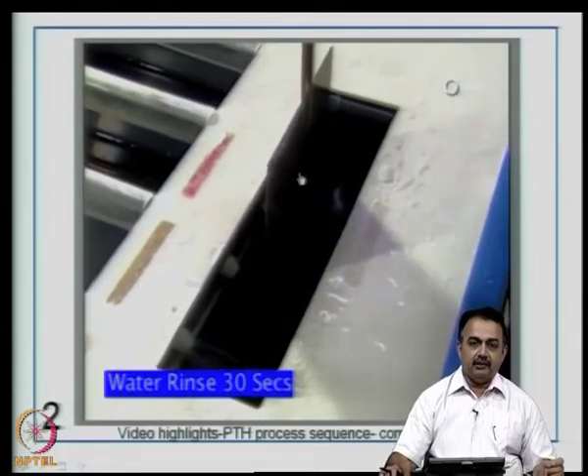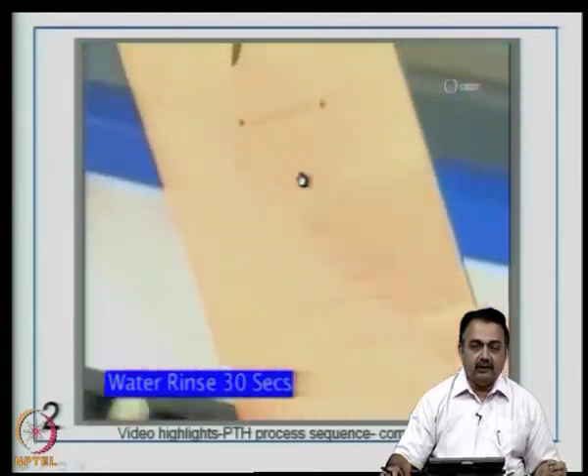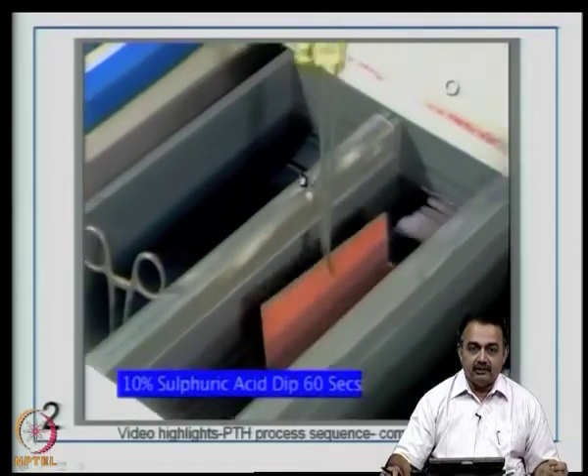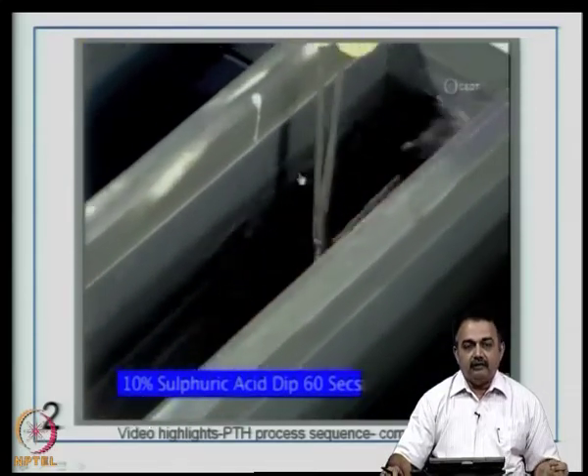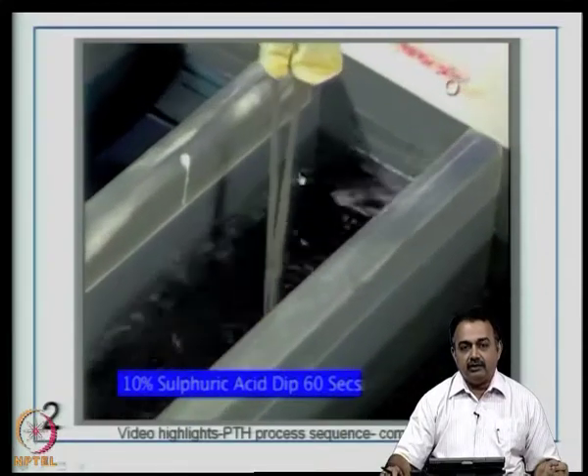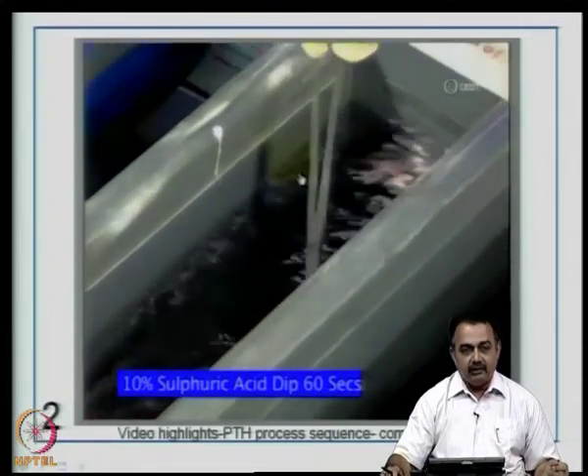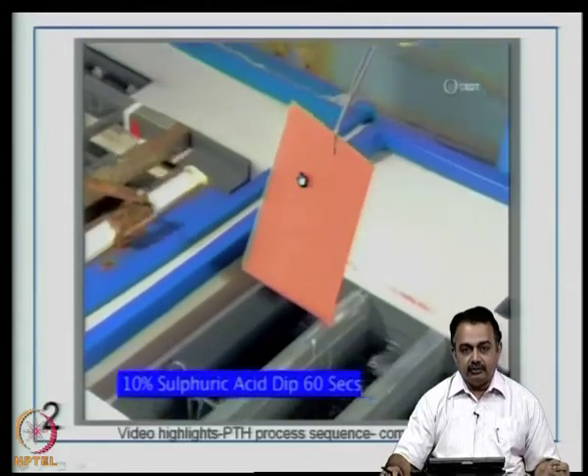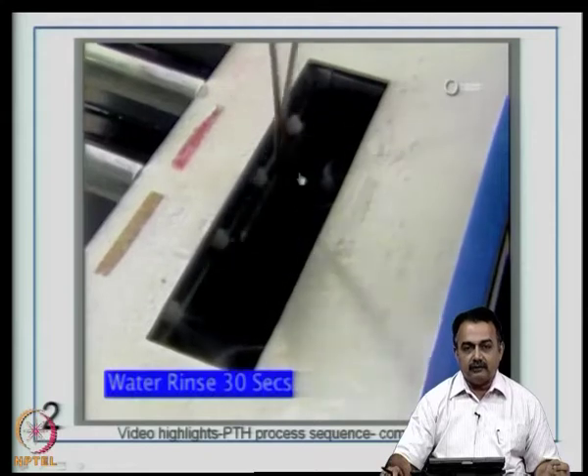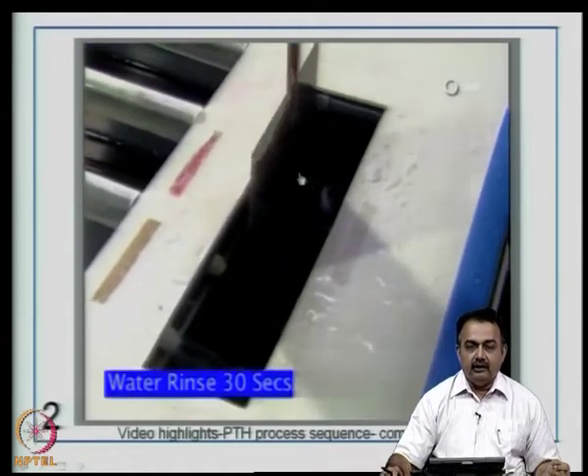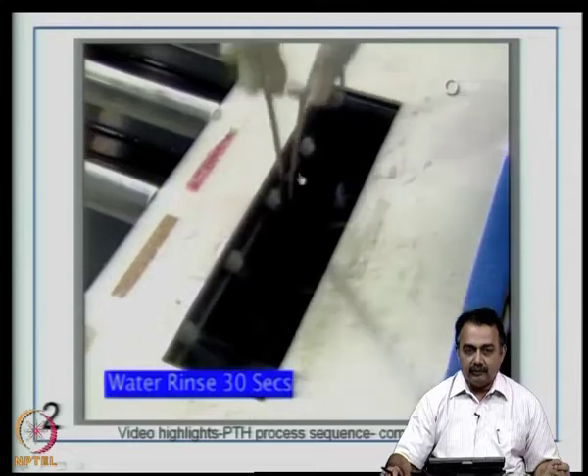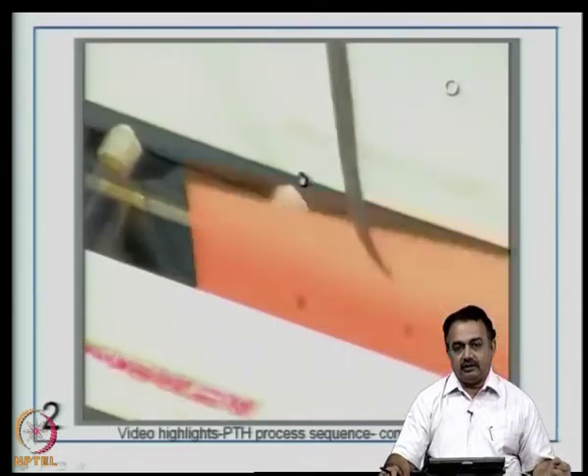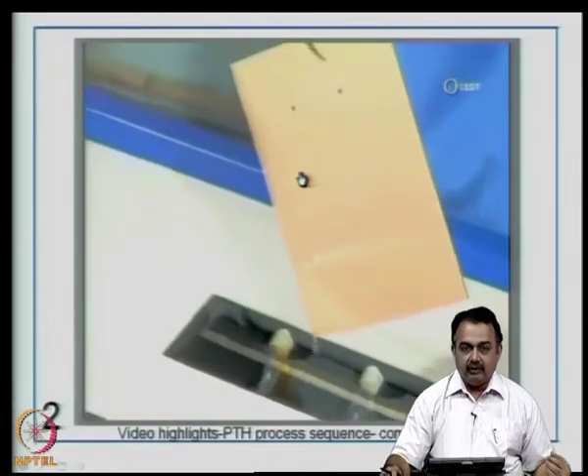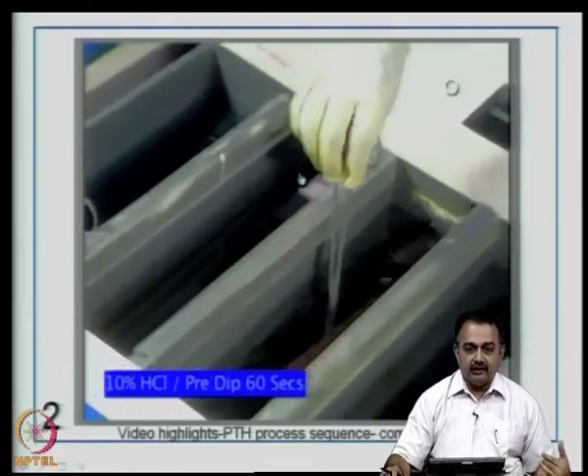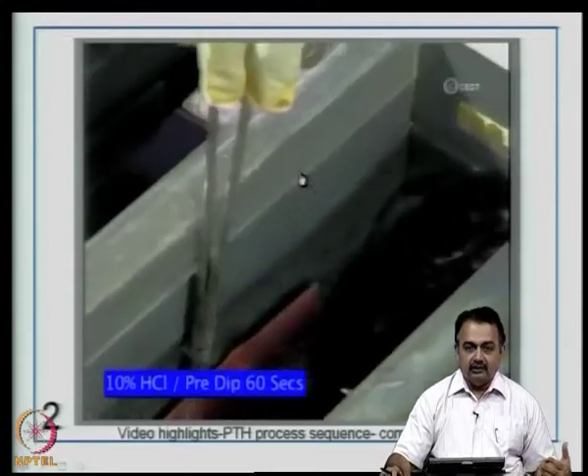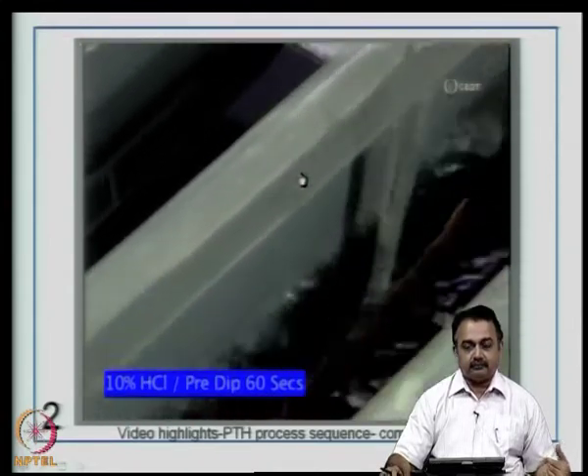Then the next step after the micro etch is a water rinse. Typically, you can use a cascade rinse or a spray rinse in some cases, as you have seen here, for 30 seconds. Then it undergoes an acid treatment in a 10% sulfuric acid dip to activate the surface with the acid. Then it is neutralized with water. So, these are all the cleaning processes. What you are seeing is basically a micro etch is a cleaning process, the sulfuric acid is a cleaning process to remove oxides and other debris that may be on the surface.